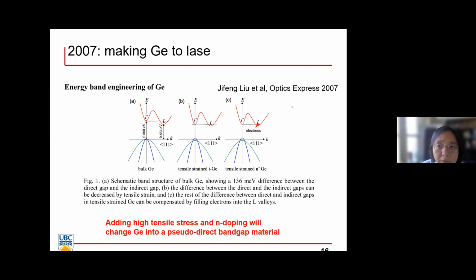So this was published in 2007. If we look at the band diagram, here is a direct band gap. It's 0.8 eV, and indirect is 0.67. So they're not too far away, about 130 meV away. So if we add tensile strain, high tensile strain, that will make the direct and indirect much